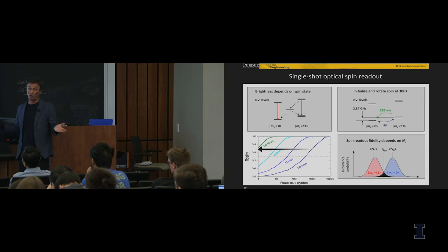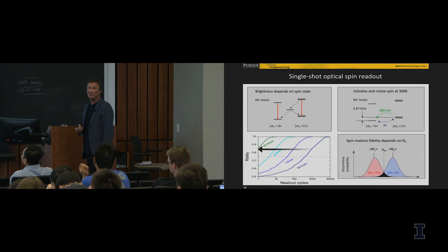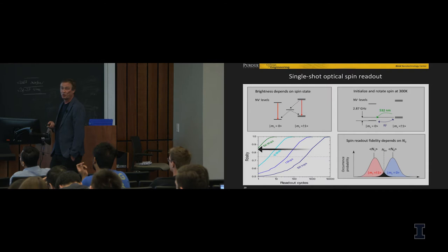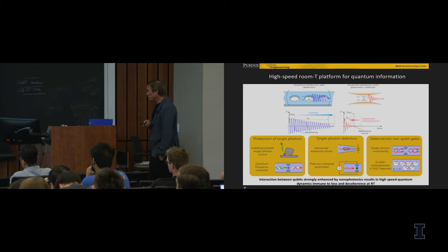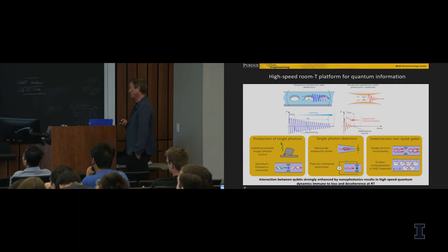However, if you use this Purcell effect, if you increase the rate with which you produce this photon, then you would be able to read the spin state within one single shot. So that's where this plasmonic speedup also could be very important to optically read the spin state. And the concept actually could be taken to other ingredients of quantum systems, like information systems or other applications.